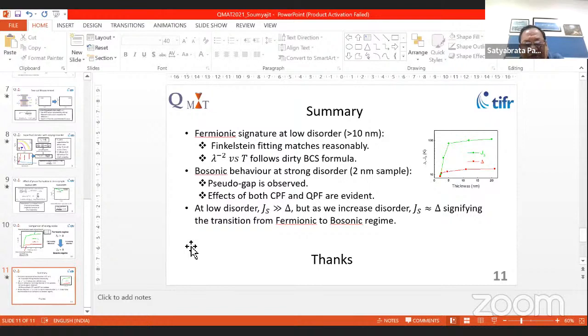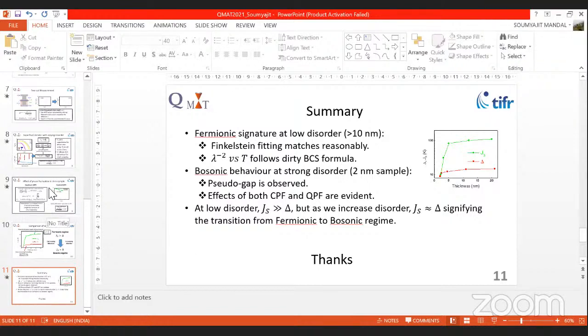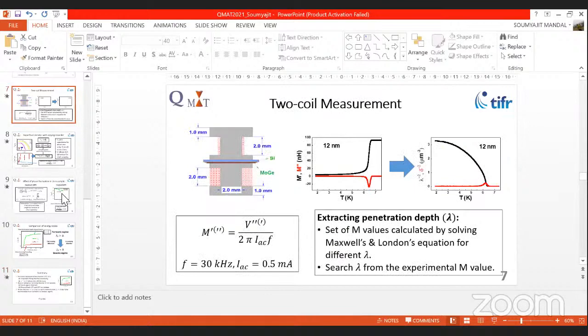Could you explain how you got your penetration depth and superfluid density from your two coil measurement? So at first we choose a set of lambda values, and we calculate from the coil parameters the theoretical M values. We have a table of M and lambda values, and from the experimental M values we just pick the corresponding lambda values. Am I clear?